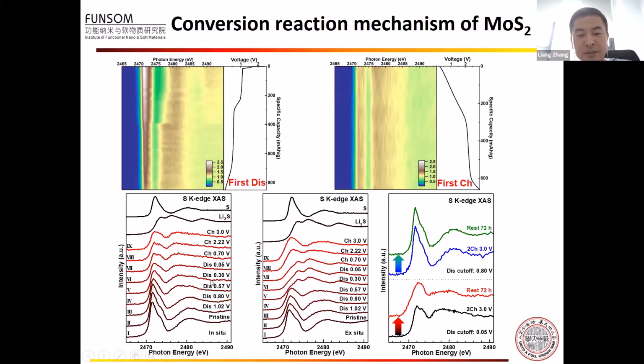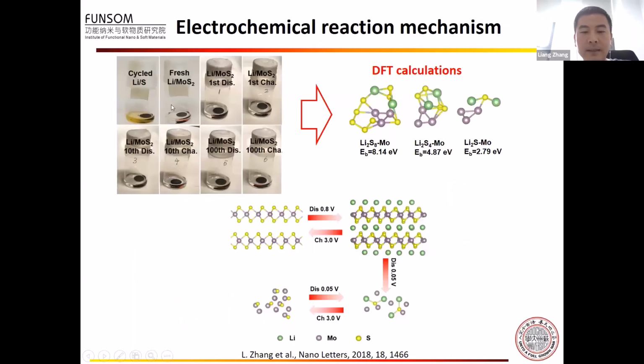But here, the in-situ results are actually quite different. This is mainly because for the in-situ results, we continuously record XAS when cycling, so the moly sulfide electrode doesn't have enough relaxation time. Further, the lithium sulfide and sulfur are insulators, which can result in sluggish kinetics of the electrode. We also use DFT calculation to confirm that there's a strong interaction between the lithium polysulfide and the metallic moly, because this strong interaction can prohibit the dissolution of the polysulfide in the electrolyte.